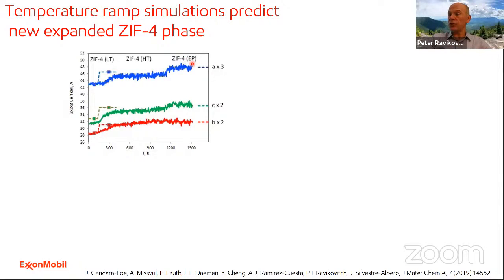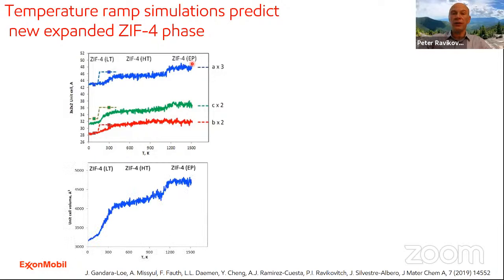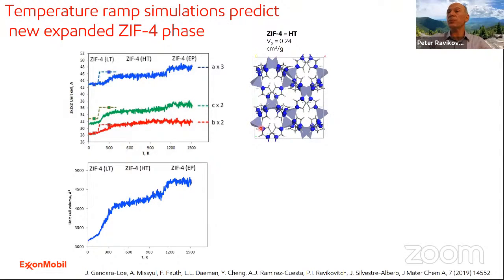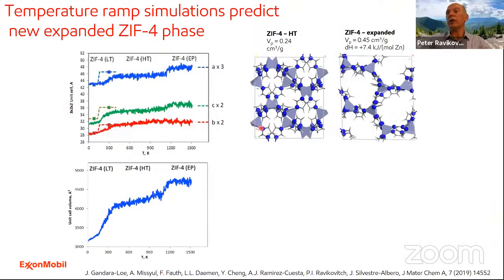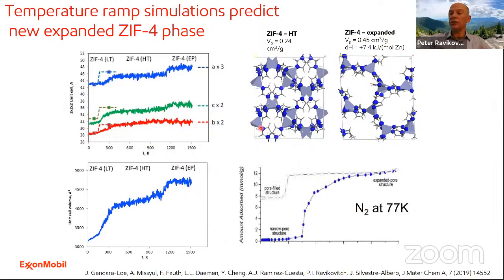And we were a little bit skeptical initially about the existence of this expanded phase until we actually found the experiments, and the experiments were done by Silvestre Albero at University of Alicante. And it turns out that if you measure nitrogen adsorption at 77K, the material starts with a narrow pore structure, nothing gets adsorbed, and then it jumps to the structure with pore volume which corresponds to this predicted expanded phase. And then upon desorption, the material shrinks again, and this corresponds to this well-known structure of the material in which it exists actually at room temperature, so-called ZIF-4HT.